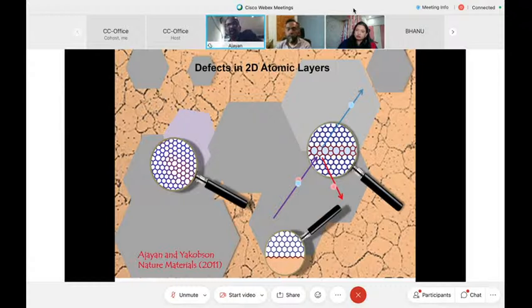Of course, when you grow these by a nucleation and growth process, you are bound to end up with defects, and that is one of the issues. Consistent results are sometimes hard to come by because of the lack of single crystal materials or experiments, particularly for electronics and electrical transport behavior. Grain boundaries have a significant impact. And grain boundaries are very interesting in these systems because if you think about it, it's a completely flat layer. And if you want to create an orientation difference, you need to think about topological defects. For example, 5-membered rings and 7-membered rings in a 6-membered lattice. And this is kind of universal, whether you look at graphene or whether you look at TMD systems.